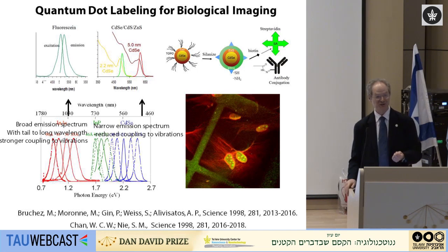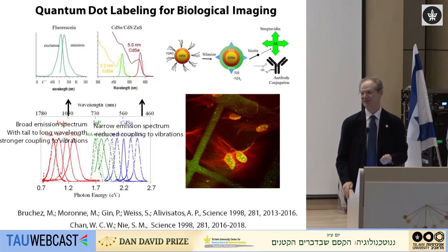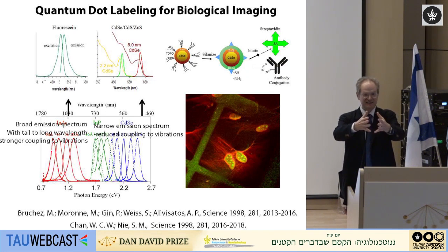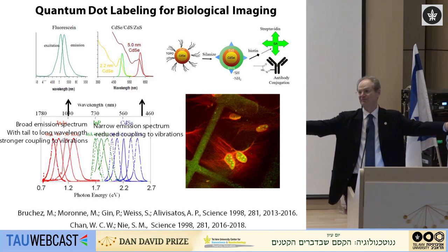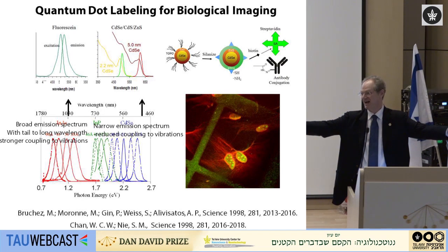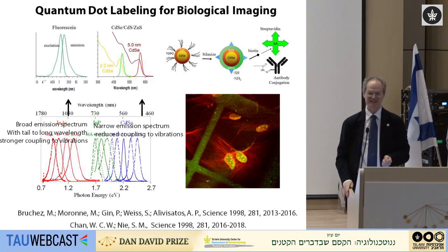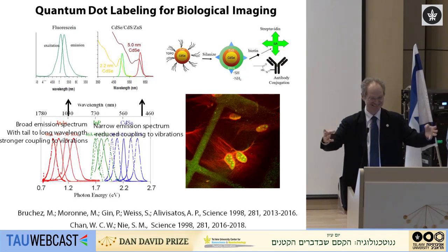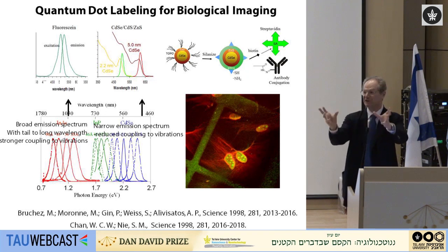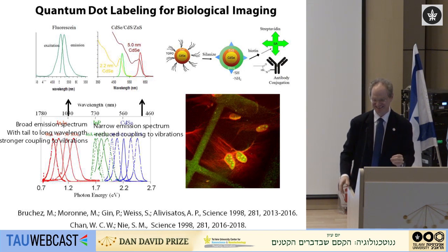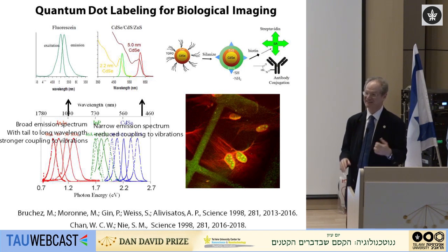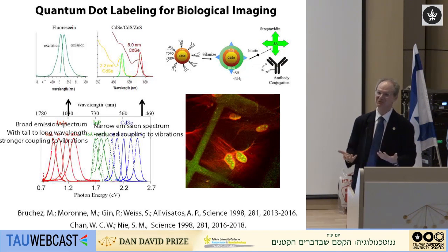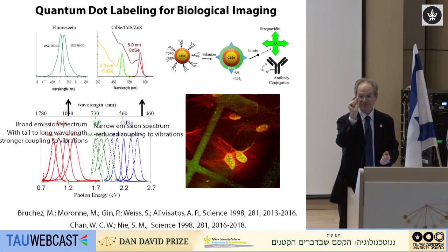So a nanocrystal is quite different because that electronic excitation is now delocalized over 1,000 or 10,000 atoms. As a consequence, the probability that the atoms will rearrange to break the crystal becomes very low. And this is fundamentally, at a very simple level, why a quantum dot is photostable compared to an organic dye. It's also why it has a more narrow emission spectrum.